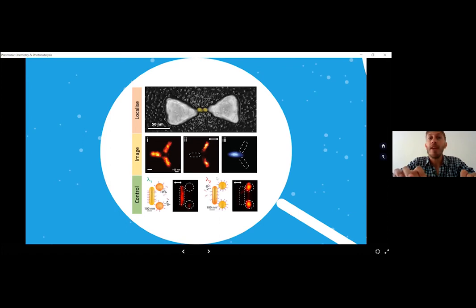And finally, once we understood how these things work, we could even show that by illuminating with two different wavelengths on the same structure, we can localize the chemical reaction on different parts of the structure. This is really interesting because it means that by changing the wavelength, we can selectively choose the space where the reaction is taking place. So we can be spatially selective on chemical reactivity, which is a really nice field, and it has not been so much explored so far.